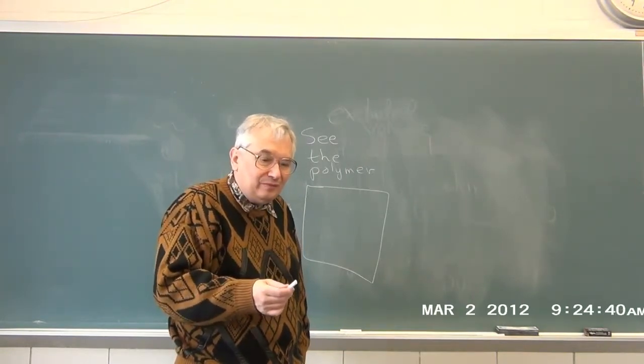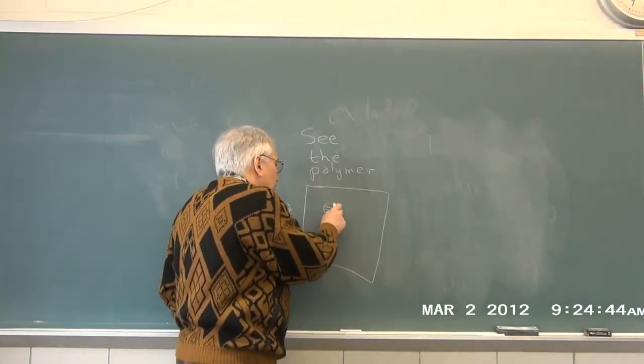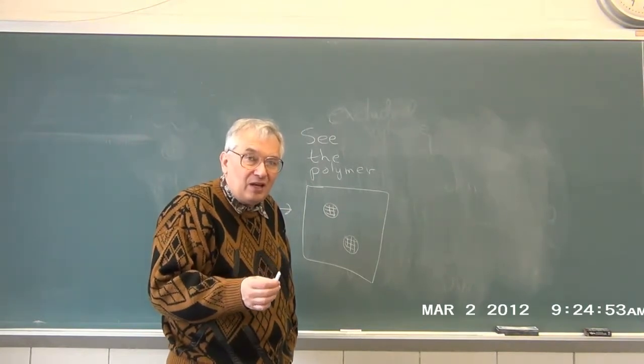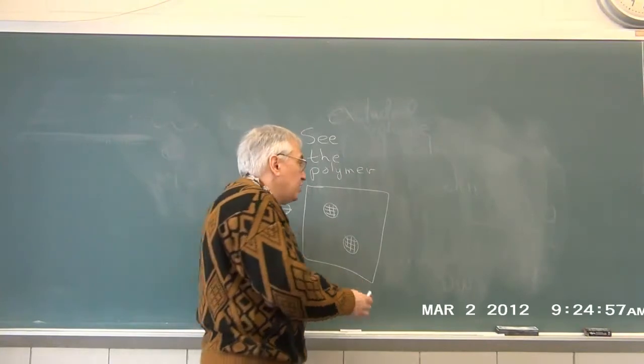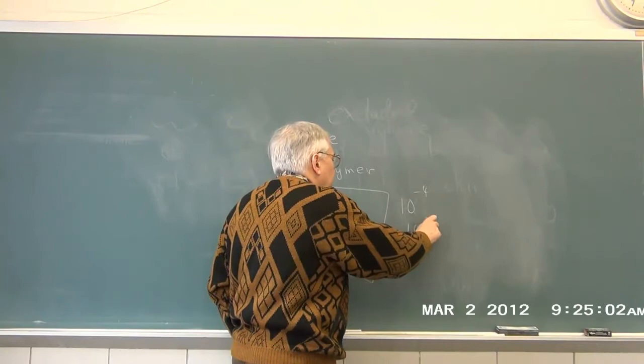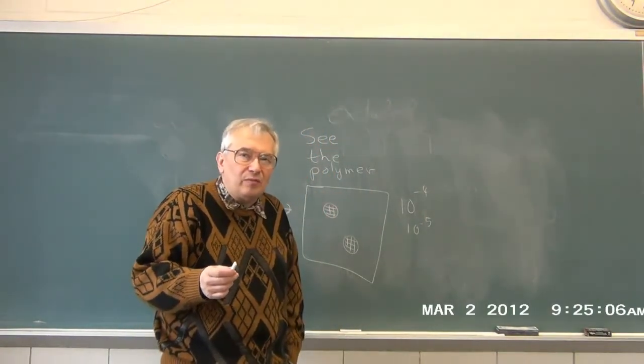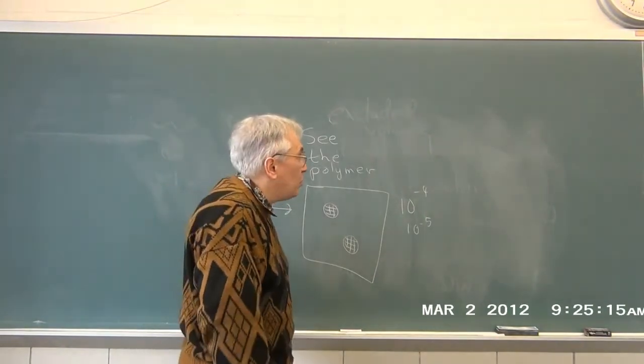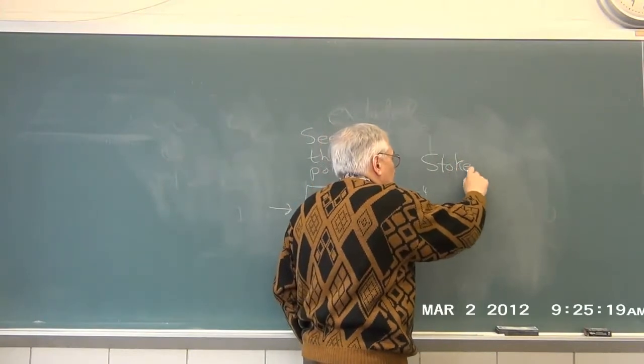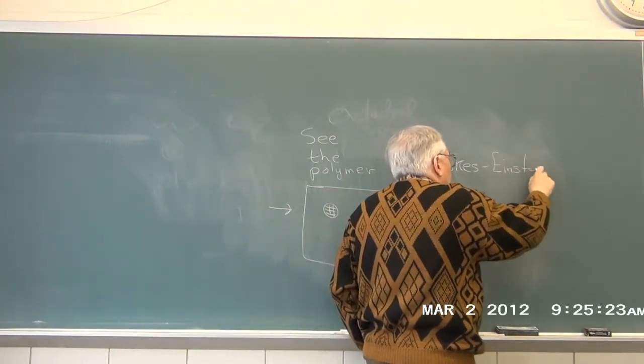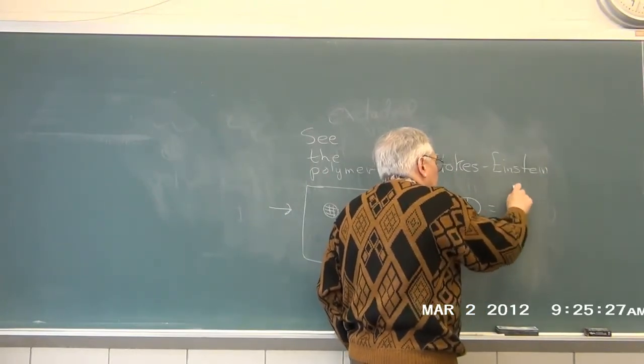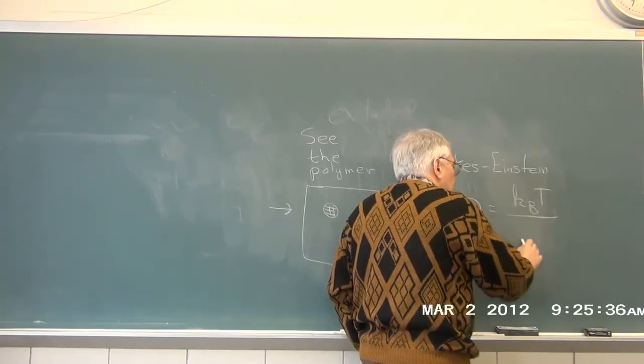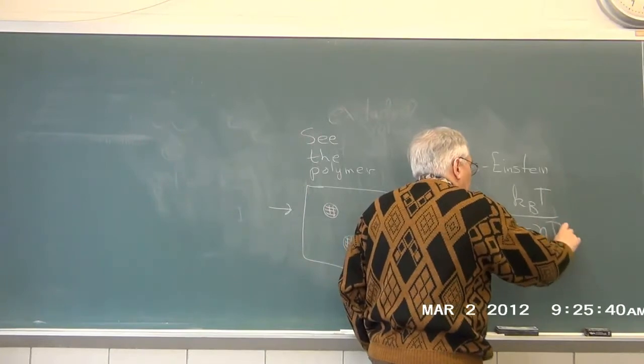You can't see any surfactant or anything else you've added to the system — it's invisible too. You can, however, see the probes you've put in. We started with polystyrene spheres. The reason we started with polystyrene spheres is we had them on hand. They're very intensely scattering, so you can easily go down to 10⁻⁴ or 10⁻⁵ by volume. The spheres are far apart from each other and don't interact at all. You are then observing the single-sphere diffusion coefficient. The starting point is the Stokes-Einstein equation: D = kT / (6πηR).